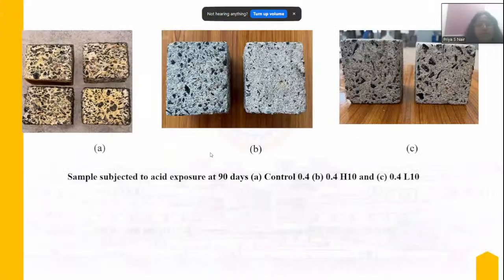In my case, I noticed that the bacterial consortium sample showed a very limited weight change and strength variation. So we can say that MICP is effective in the chemical aspect. These are the images of the control, the higher consortium concentration, and the lower consortium concentration after 90 days. We can see that the control is more vulnerable, more susceptible to acid attack, but the others are not much.